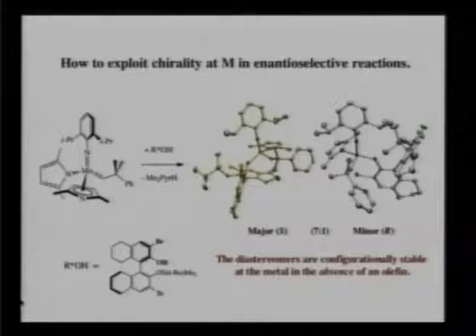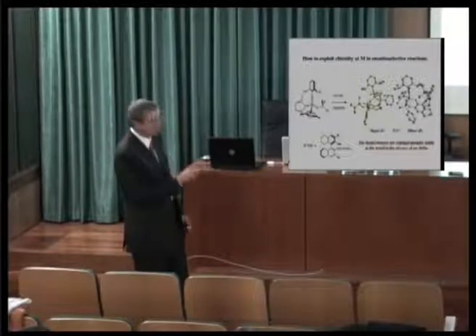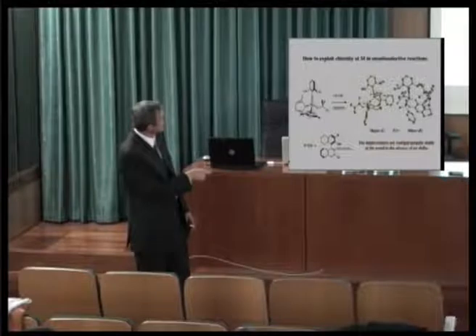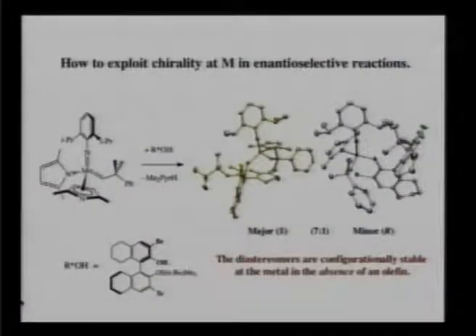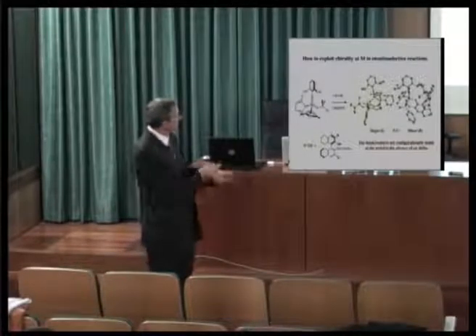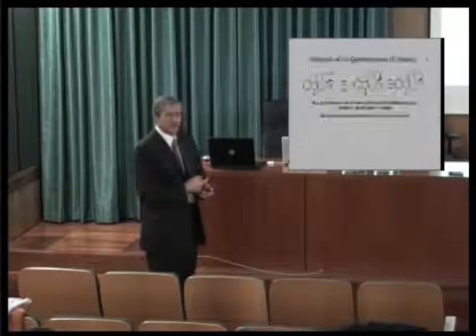In order to control that chirality, we have to make diastereomers. So we attach an alcohol that itself is enantiomerically pure, and then you can have chiral compounds that have one chirality at the metal center and a fixed chirality. This one happens to be R in the ligand, or the other configuration at the metal and R in the ligand. So this is S at the metal, R in the ligand, R at the metal, R in the ligand. These are configurationally stable. They can be isolated and characterized. These are crystal structures, and then used in various reactions.